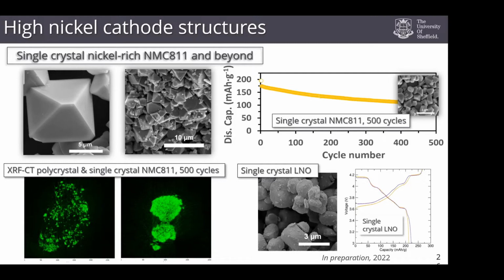These are the challenges of cobalt, and ideally we would like to replace cobalt with another element that can do its job, structural stability, and reduce our reliance on these kinds of challenging elements, and ideally move to something where we're just using lithium nickel oxide. This is a challenge because nickel oxide isn't always very stable, but we've been able to do some tricks in our labs in Sheffield and around the country to generate single crystals of lithium nickel oxide that are giving us huge improvements in capacities. And we're starting to see how we can maintain those capacities over time by looking at the chemistry again, trying to stabilize those layers and to introduce concentration gradients at the surface.